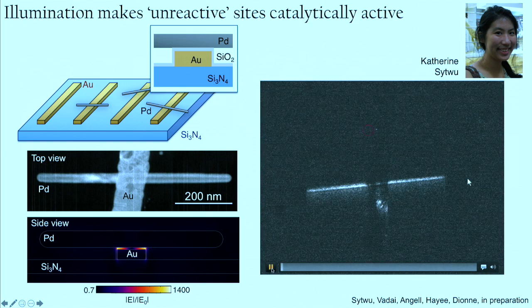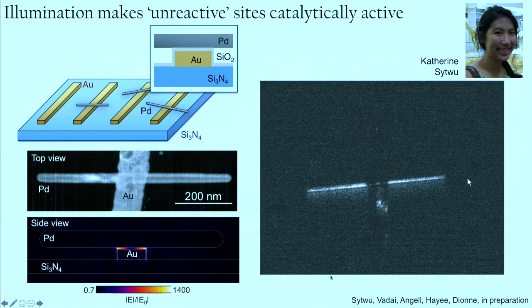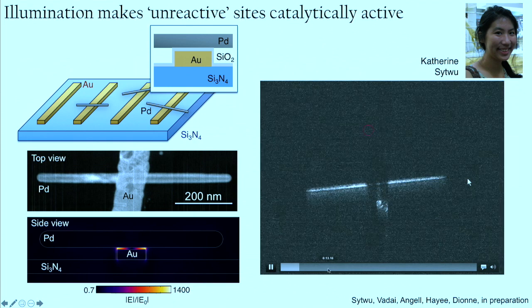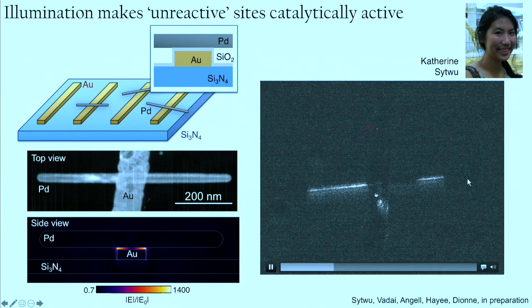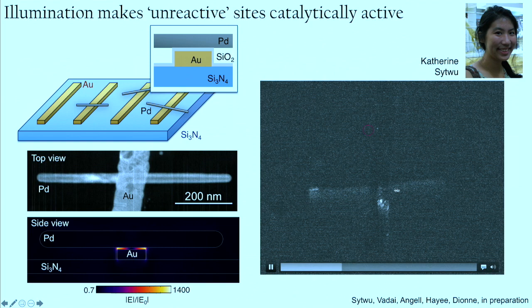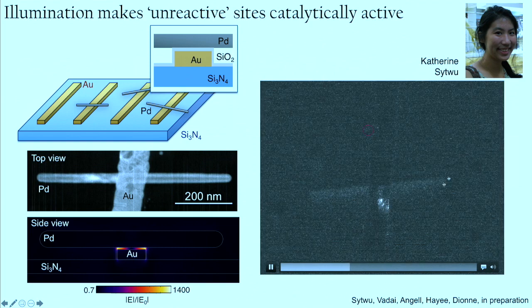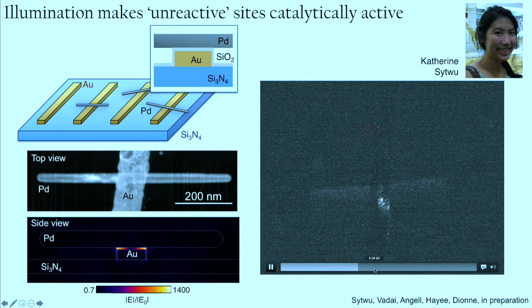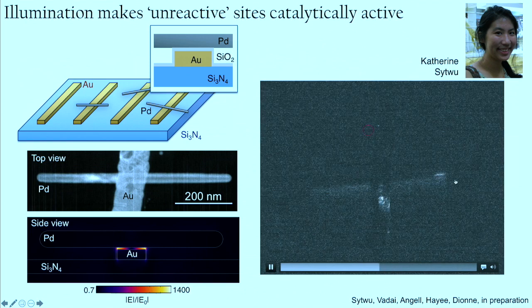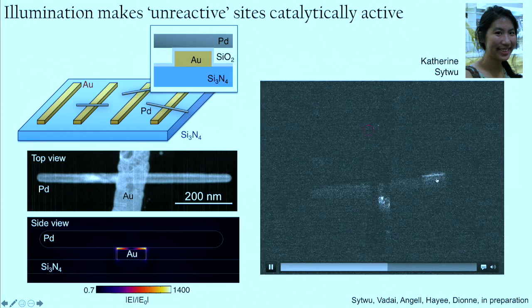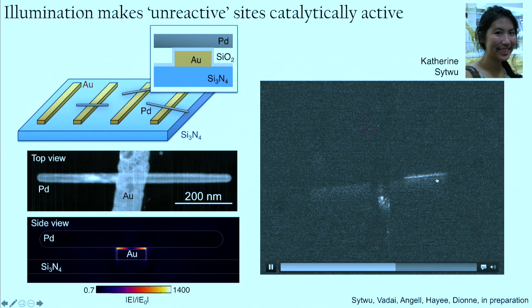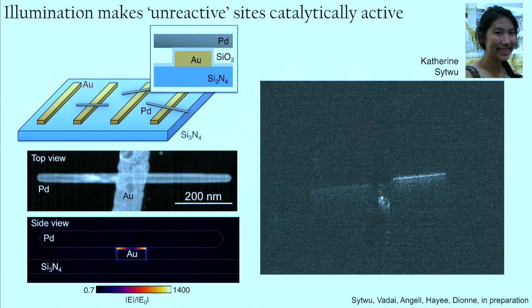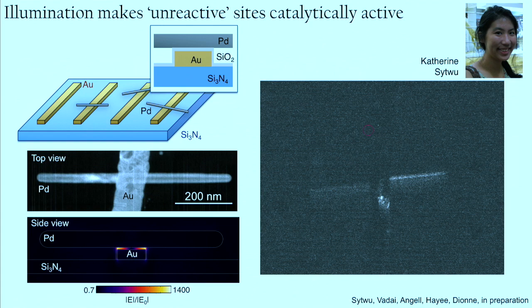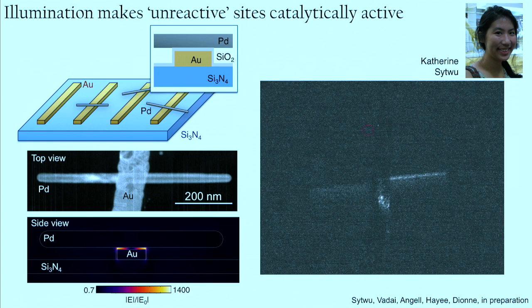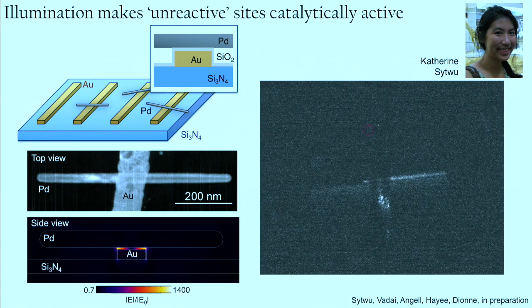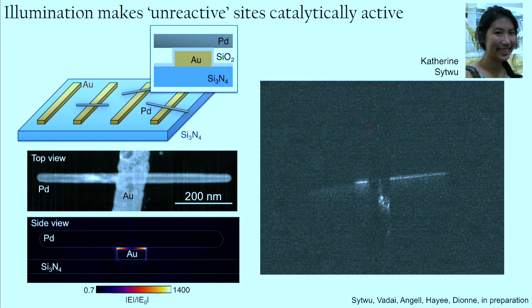But what we found is that when we turn the light on, so here I'm just showing you a video. I'll turn the light on. I think it happens right around here, that you can see the hydrogen's going away now from the middle of the nanorod. And then when we turn the light off, which I think you'll see here at about 27 seconds, the hydrogen now comes in from the tips of the nanorod. So I think this is a pretty exciting opportunity to be able to engineer photocatalysts where we can make more of the surface area active and use more of the material, ultimately to increase reaction rates.